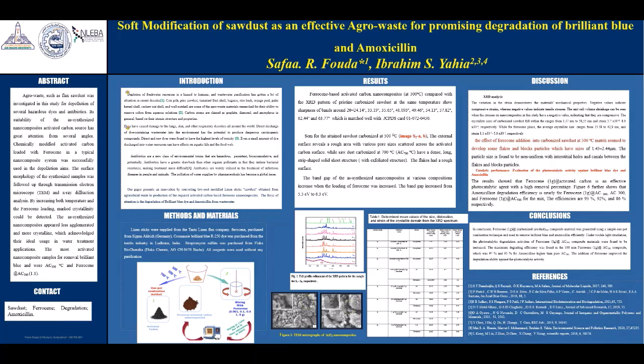The XRD diffraction showing that activated carbon which carbonized at 700 is quite similar to that activated carbon which carbonized at 500, and showed that the peak at 2 theta 26.5 is disappeared compared with that for activated carbon at 500. In addition, the average grain size is decreased than that when carbonized at 300.